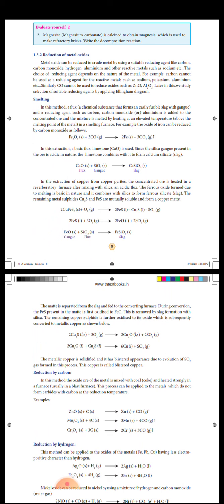During conversion, the ferrous sulfide present in the matte is first oxidized to ferrous oxide FeO. This is removed by slag formation with silica. The remaining copper sulfide is further oxidized to its oxide, which is subsequently converted to metallic copper as shown below. 2Cu2S liquid or solid plus 3O2 gas gives 2Cu2O liquid or solid plus 2SO2 gas. 2Cu2O liquid plus Cu2S liquid gives 6Cu liquid plus SO2 gas.